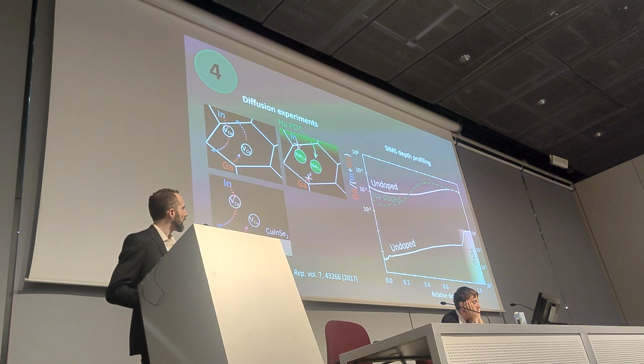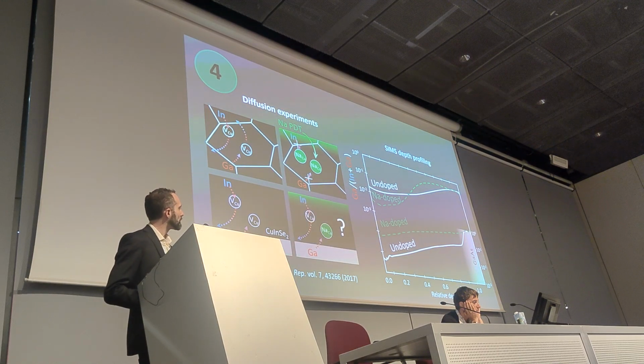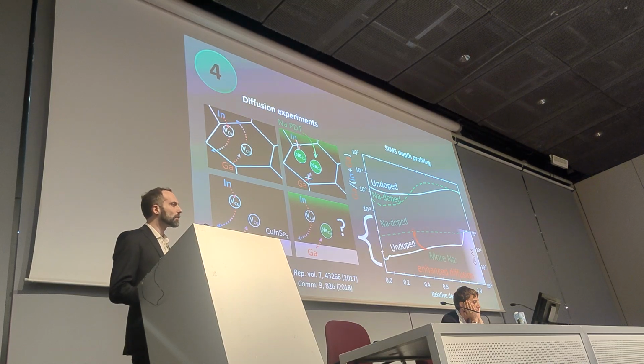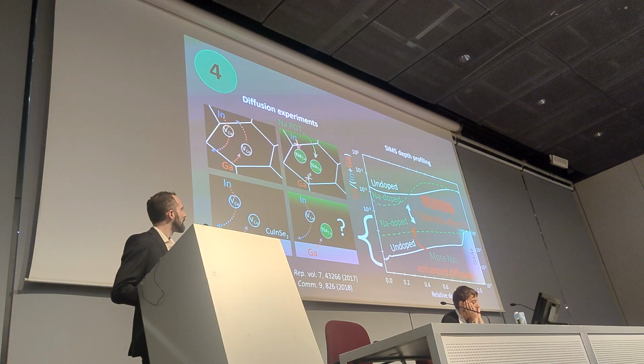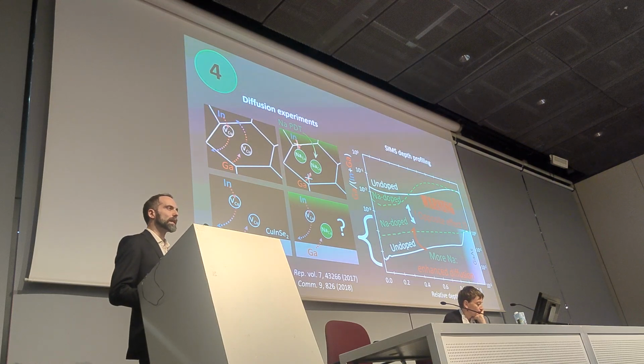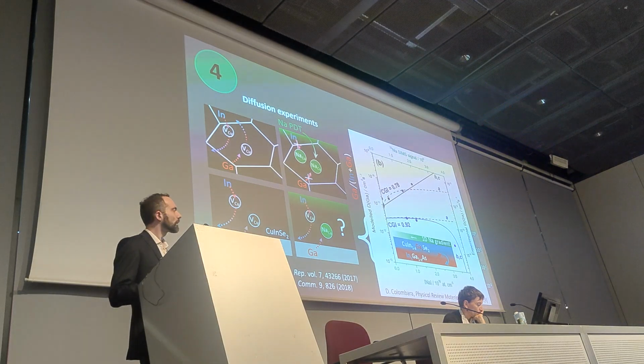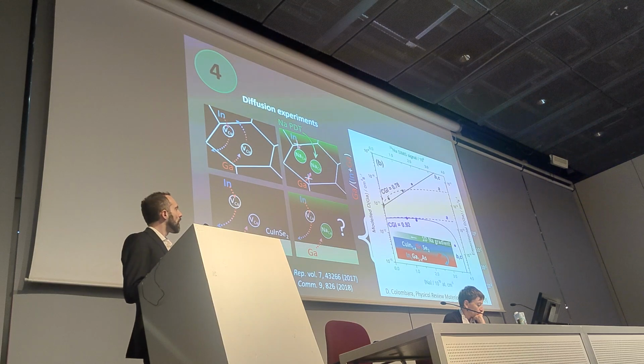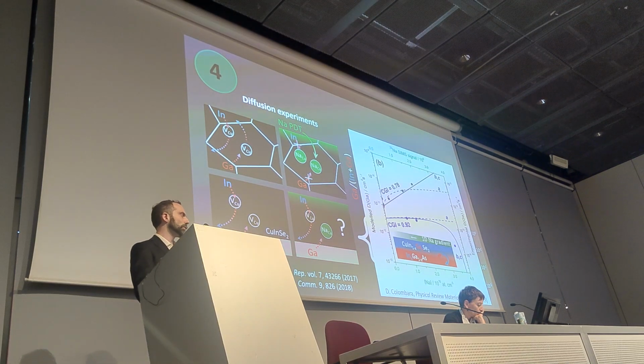So this is what we have. And what we have when we add the sodium, surprisingly, is the opposite effect of what was known for 20 years in the polycrystalline case. So initially we were very tempted to say, yes, it's a question of grain boundaries. But in fact, a more complex experiment turned out to tell us it's not the case. It's not a question of grain boundaries or not. It's a question of how much copper and sodium you have.